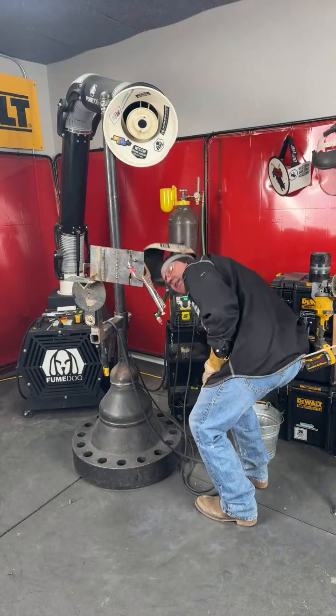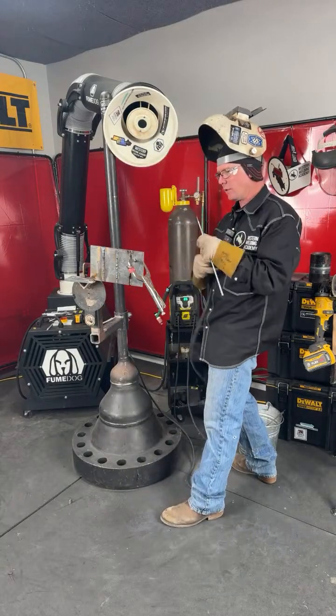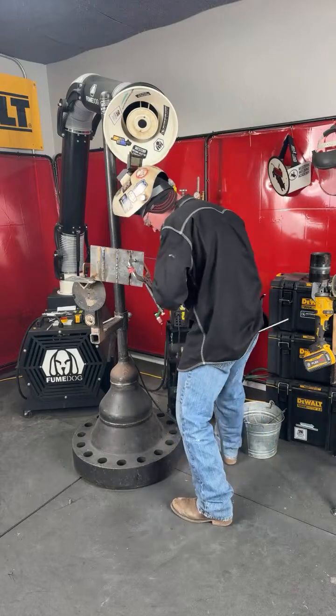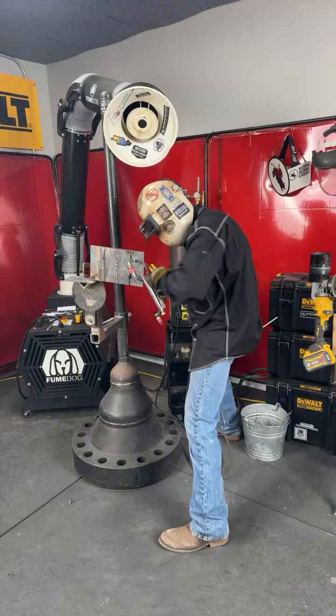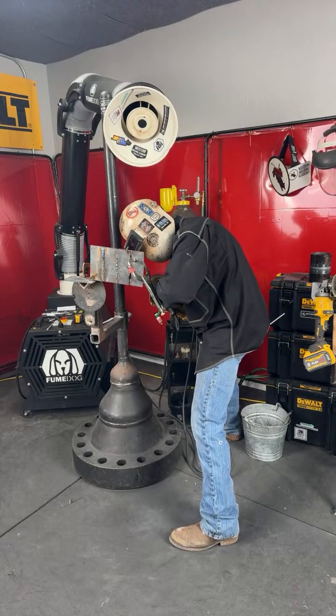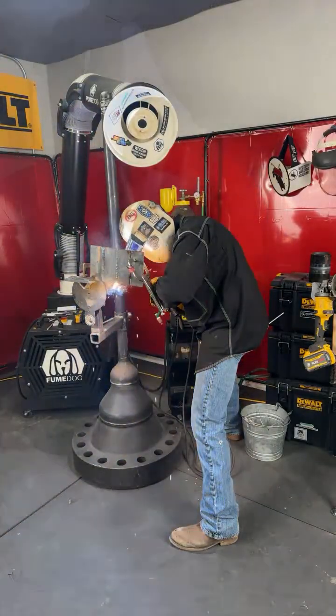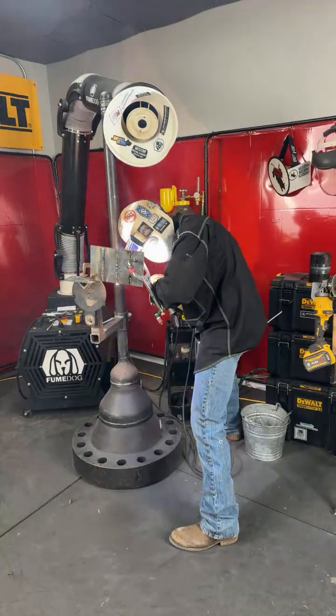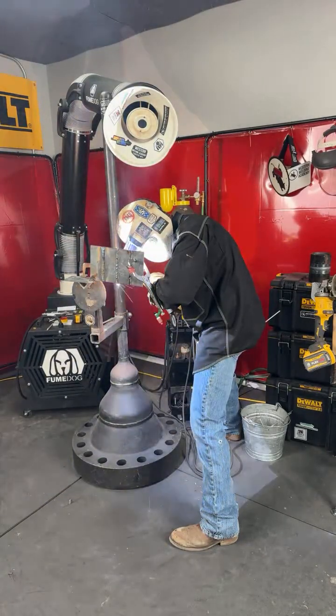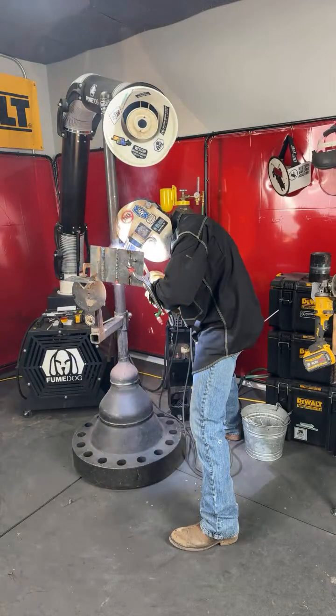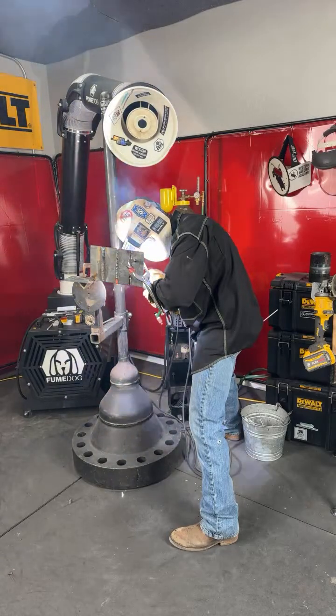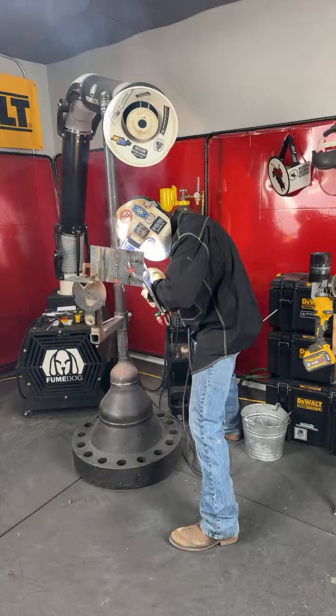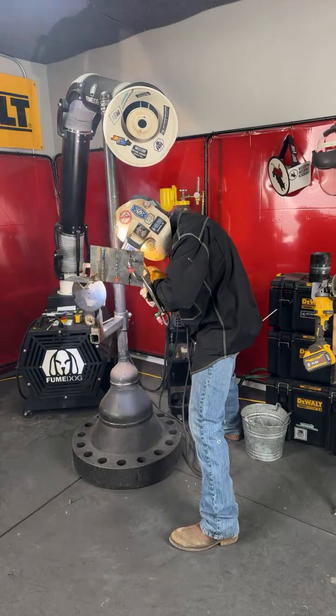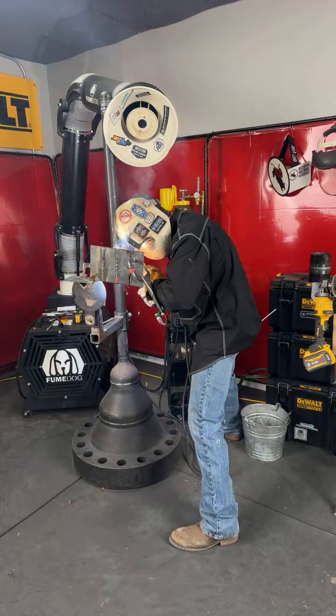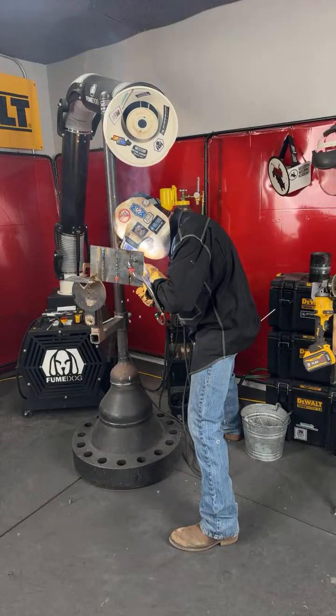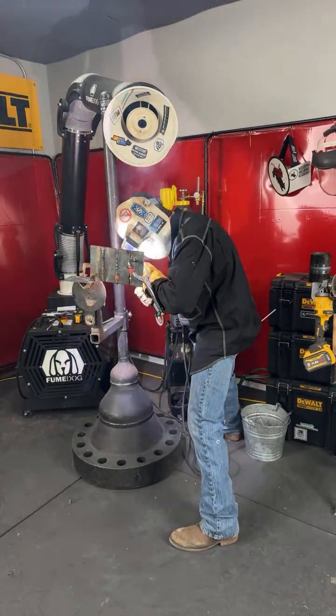I'm gonna run the hot pass right there. Kind of got myself in a corner here. Backed in the corner like a wildcat. Ready? I don't know if you guys can see that root getting really hot. As long as you don't long arc, keep that puddle between your arc and the rod, you'll be all right. But if you try to move too fast and you get that arc out in the middle of your root, you're going to burn a hole. If you pull that rod back and you long arc real bad, it's going to overheat, burn a hole.